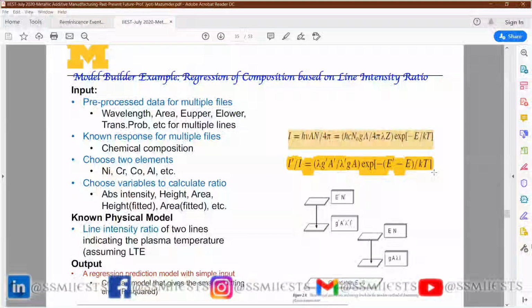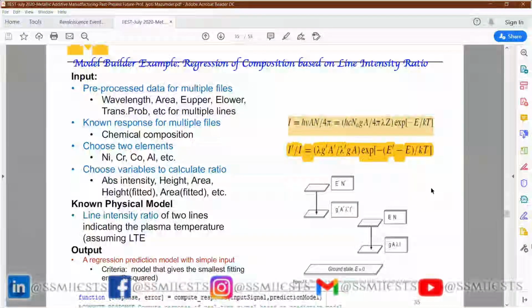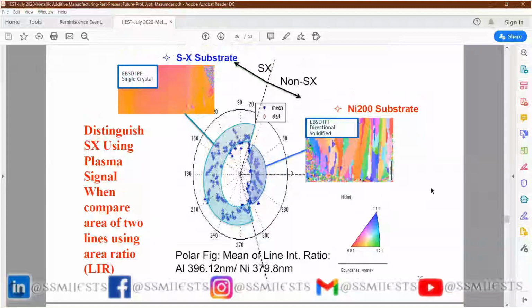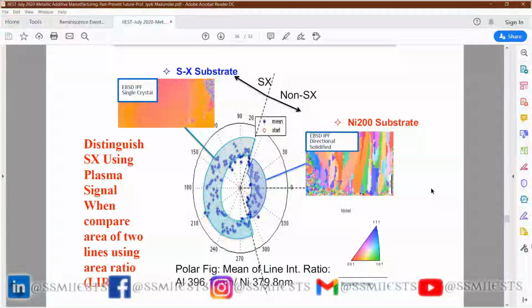Another technique we did to make sure whether you're in a single crystal or polycrystal, we deposit material on two base plates. One base plate is single crystal, another is polycrystal. And you can see the material deposited on a polycrystal, same process parameter, everything. The non-single crystal is giving you polycrystalline growth, whereas the single crystal base is giving you single crystal deposition. So by using this kind of technique, we try to identify and differentiate the spectra deposited on a different base plate, and by comparing that, we can find out whether I'm growing a single crystal or polycrystal.